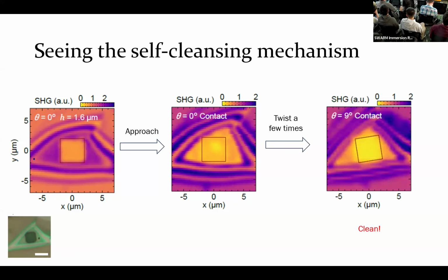But what we can do is let them remain in contact and then we twist and twist. And what that does is it actually squeezes out the trapped air and junk if you do this a few times. And indeed, after doing that, what we're seeing is that the interface becomes much more uniform and cleaner. So this is also known as the self-cleaning mechanism for 2D materials, because these 2D materials have atomically flat interfaces, and they really like to be intimately contacted. But if there's some trapped air, then it cannot get the intimate contact. But after you squeeze it, it has a tendency to squeeze out the dirt on itself, and get a cleaner contact just by itself.